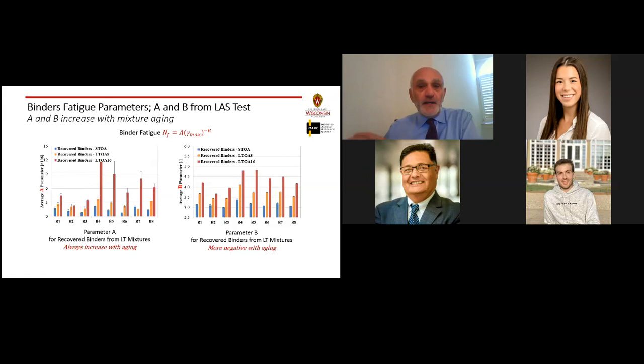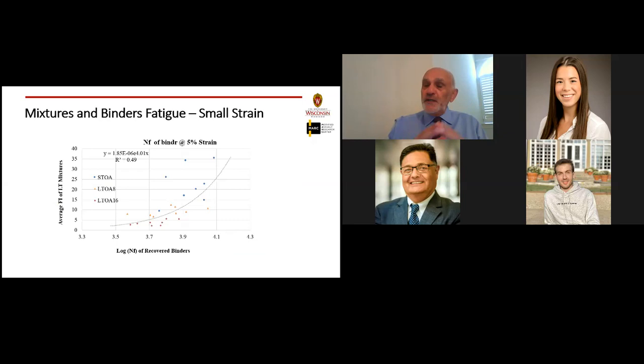The problem here is, are there relationships? So what we did, we looked first at the relatively small strain. We tried to correlate the flexibility index of the mixtures with the Nf estimated at 5% strain, not a very high strain. And you can see there is some trend, but the correlation is not strong. In fact, here I have an Nf value of about 4, and the mixture flexibility index was an order of magnitude different, from about 8 to almost 36, or four times, and so on.